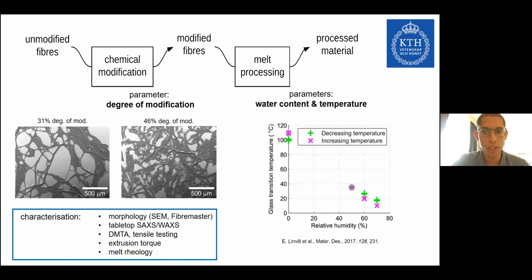And then our strategy is quite straightforward. So we will prepare chemically modified fibers to varying degrees of modification. In the SEM images, you can see the 31% degree of modification material, and also a sample of material that has been converted to 46% degree of modification. And even at high degree of modification, you can see that the fiber-like structure remains intact. Well, the material softens, and you can see some spreading out on the surface that is a result of that